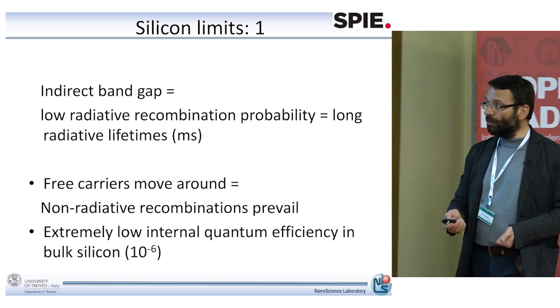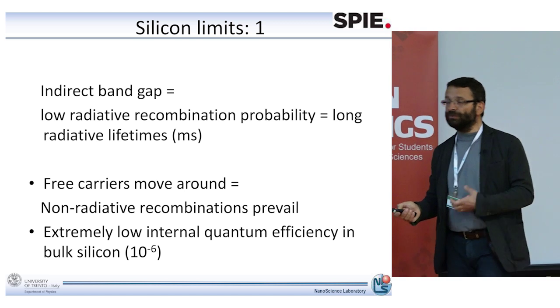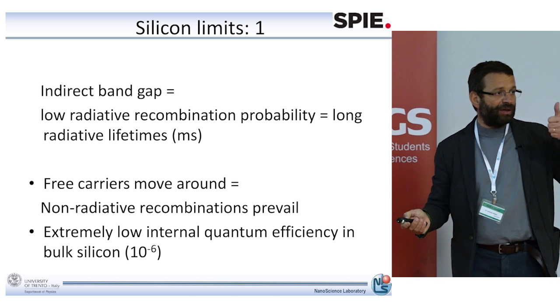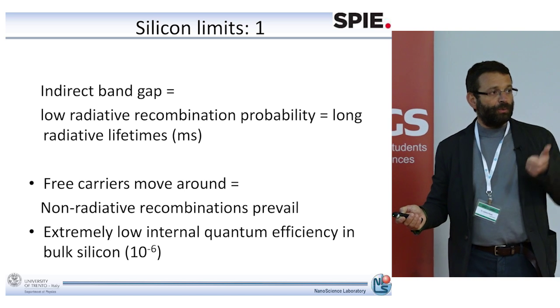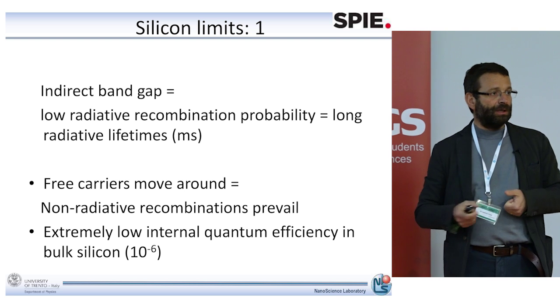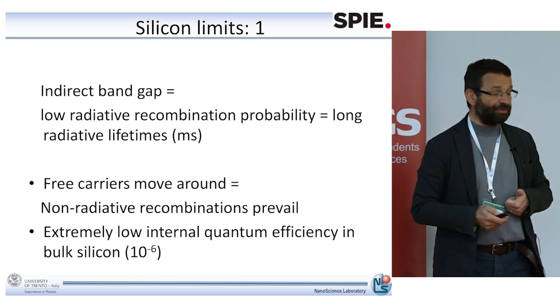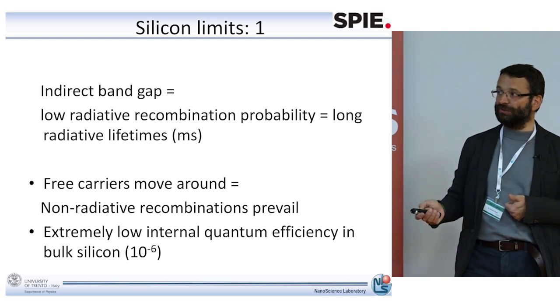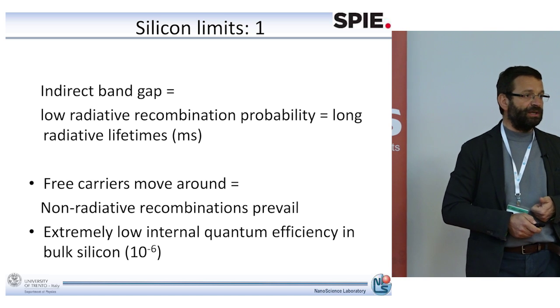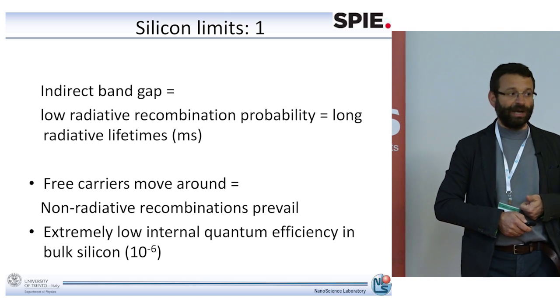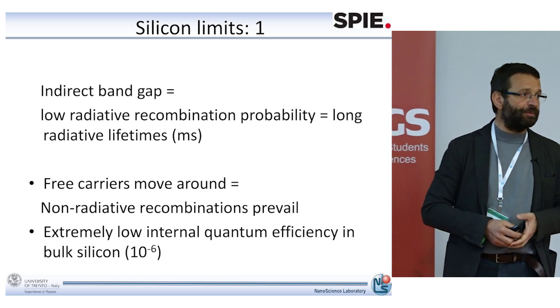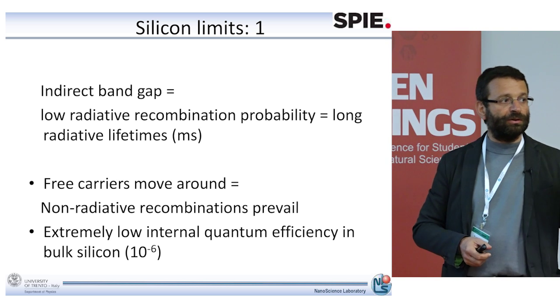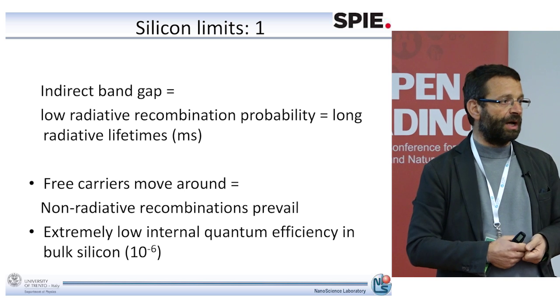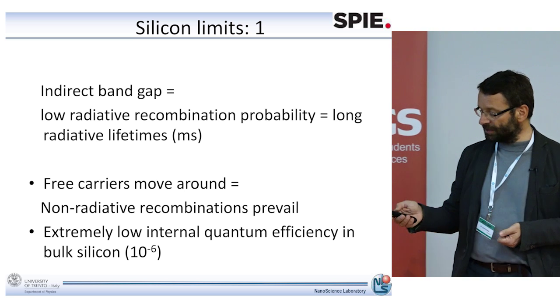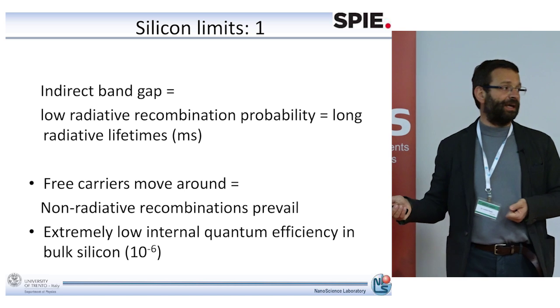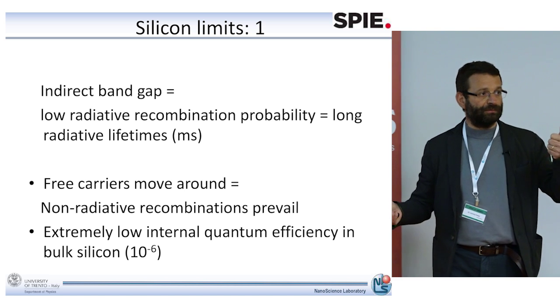And this is the reason why in silicon, in order to have one emitted photon, we need to excite 1 million electron-hole pairs. This means that the internal quantum efficiency in bulk silicon is extremely low, 10 to the minus 6. Gallium arsenide, typically 50%. So you excite 2 electron-hole pairs and you get 1 photon out. Here, we need to excite 1 million electron-hole pairs in order to get 1 photon.